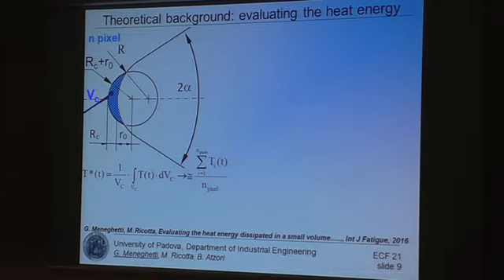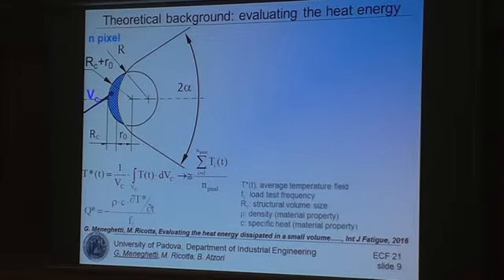And at this point, imagine you suddenly stop the fatigue test. What happens is that the material cools down, and if you take the thermal gradient measured just when you stop the fatigue test, you will obtain the average value of the dissipated energy. So you need just to know the material density, the material specific heat, the thermal gradient measured when you stop the fatigue test, and you need to know the load test frequency.